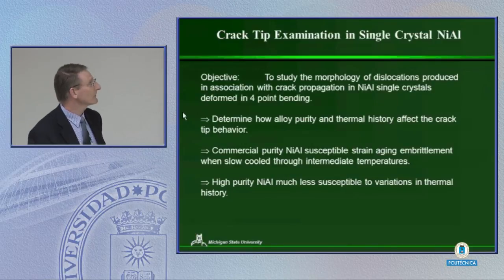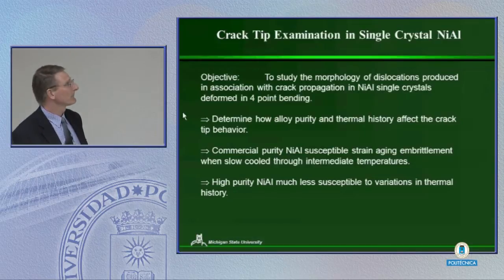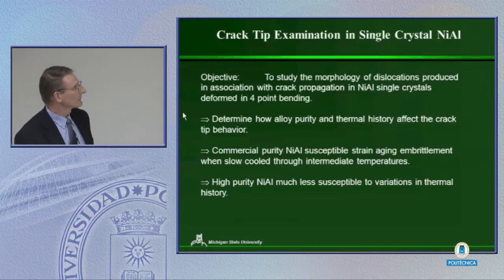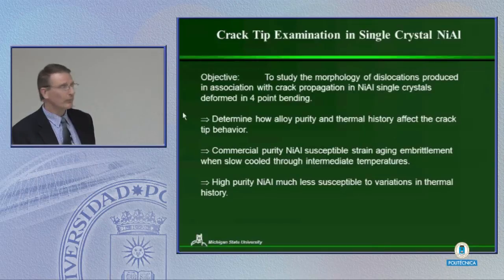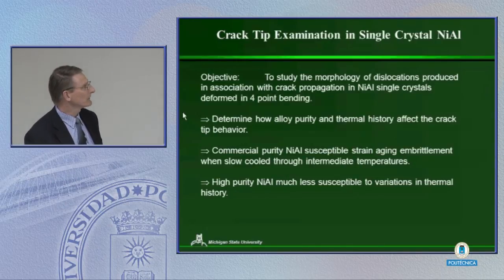The first thing I want to show you is how we can look at crack tips. And this happens to be nickel aluminum, which 20 years ago was a very exciting thing for people to look at. And we've been looking at this more and more over the years. What we've done is we deformed these with 4-point bending. In this particular case, I won't go into a lot of details about this, but I want to show you really the capabilities of the technique.